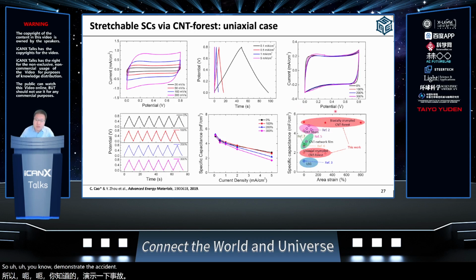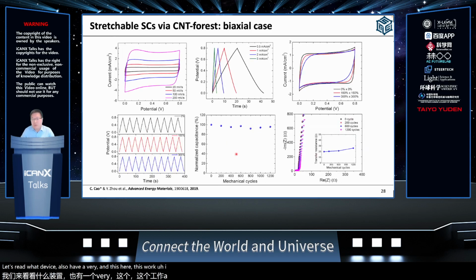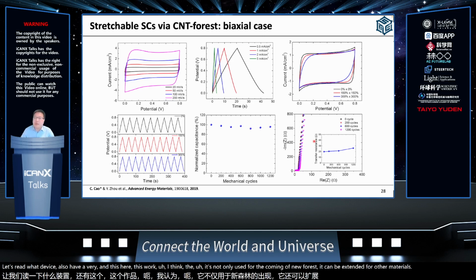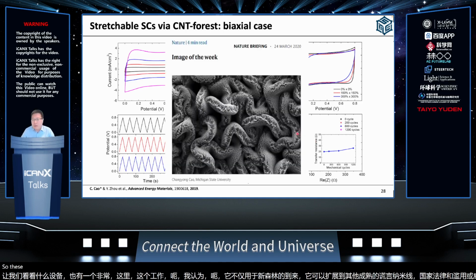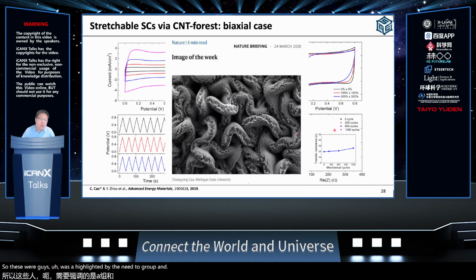demonstrates excellent electrochemical performance. The CV curves and the charge discharge curves are not affected much by the applied strains, even when the applied strains are larger than the pre-strains we used. This is for the biaxial case, and the biaxial stretchable device also has very good performance. And this work is not only used for the carbon nanotube forest. It can be extended to other materials like nanowires, nanorods, and nanotubes for stretchable devices. This work was highlighted by Nature Briefing and reported by many other outlets.